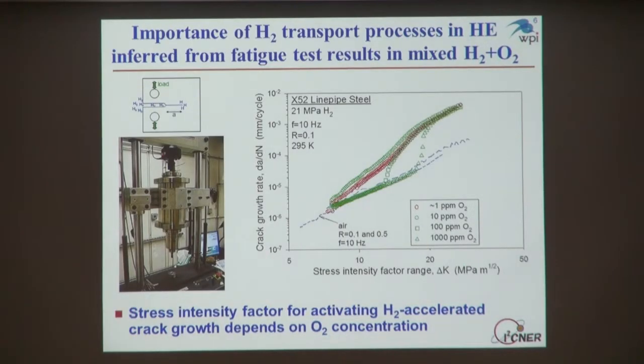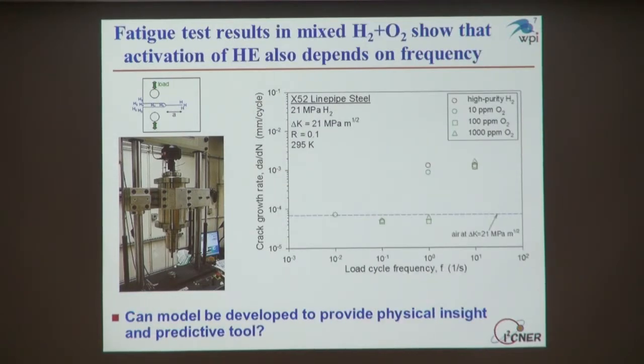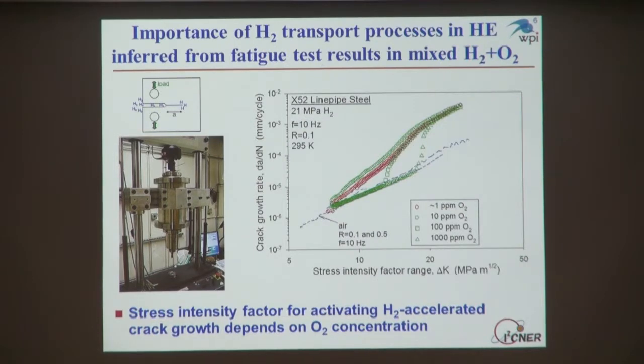So I'm going to start off by showing you some experimental data. This is data that I've shown before. There's some additional data that I'm going to be showing in this talk as well. But just to give you some appreciation of what we're seeing with this data, these are tests that were done in high-pressure hydrogen gas environments. These were done using these typical types of specimens that we would use in the laboratory. These are specimens that we use to apply cyclic loading. So we're interested in studying the effects of hydrogen on the fatigue crack growth.